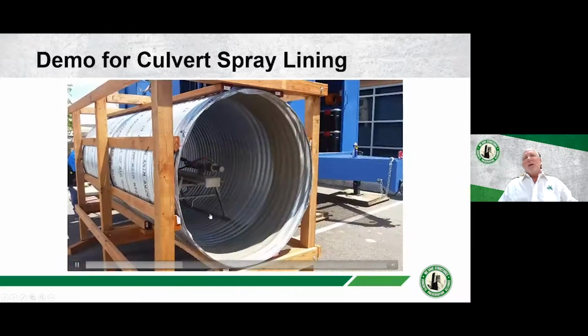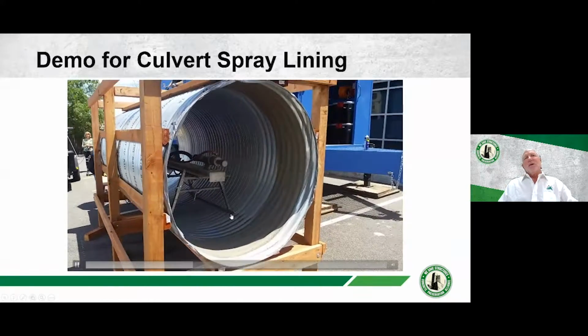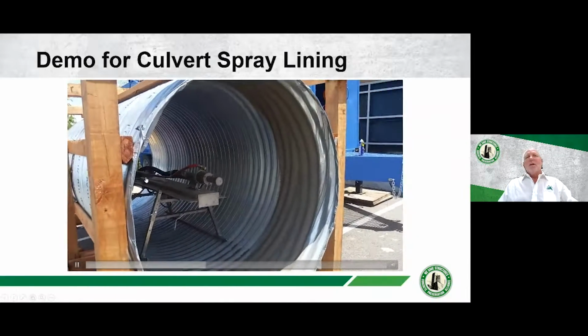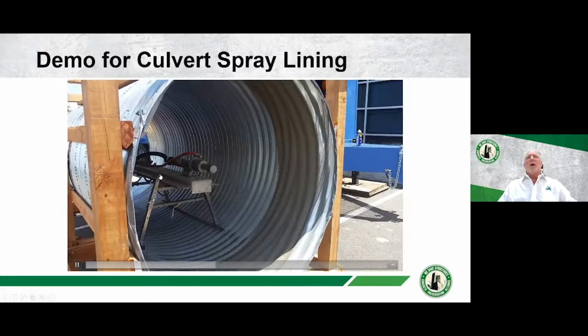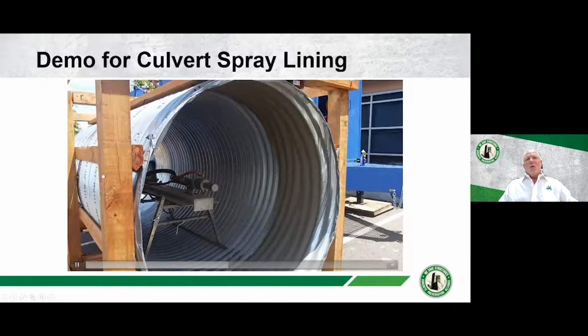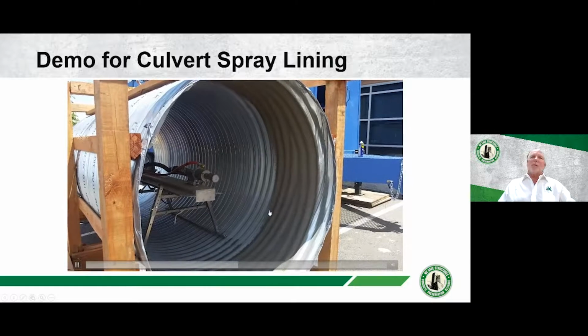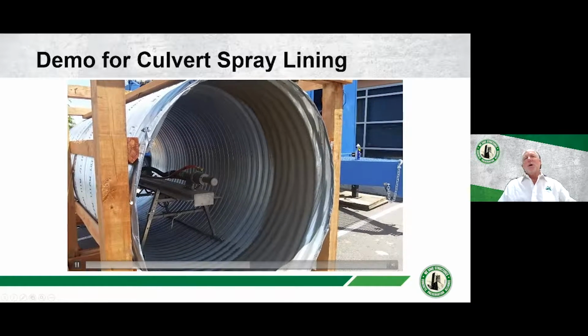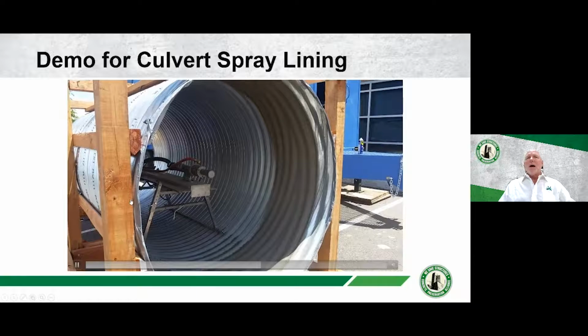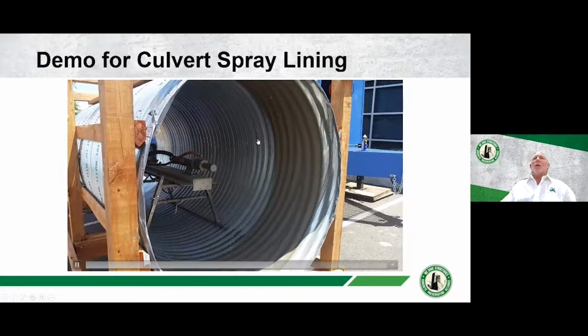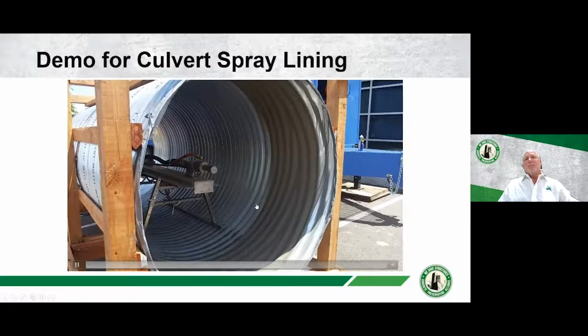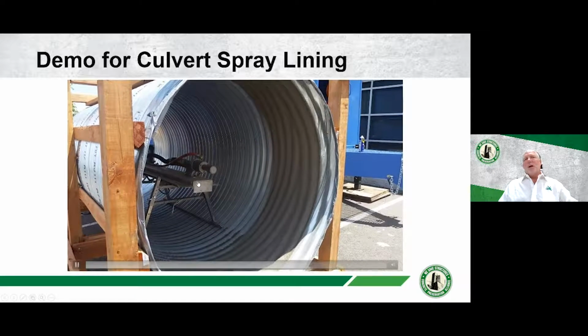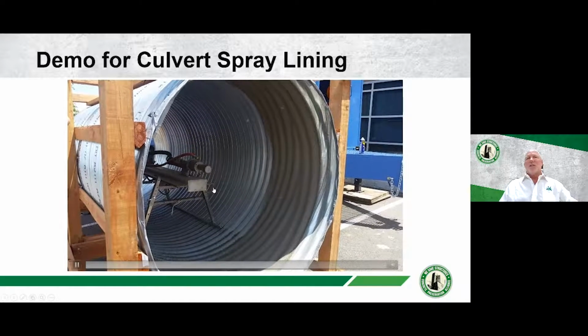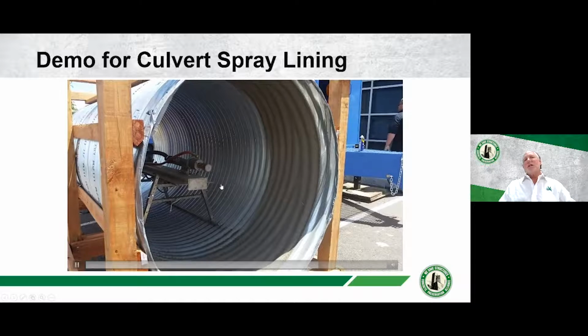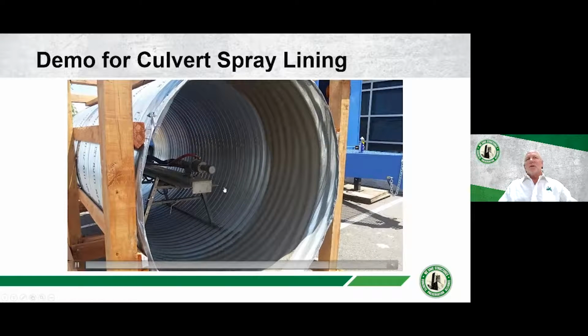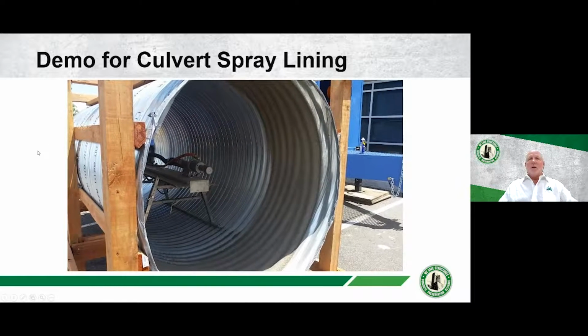The way it works is that this sled here is pulled back slowly at a specific rate. And we actually have calculations to say, okay, with this certain amount of material being pumped down the line, what speed do we have to pull this sled back so that we get a uniform thickness on the wall? And so that works out really well. Generally, with culverts, we're going to be spraying thicknesses of somewhere between half an inch and 1 inch per lift, and that all depends on how much material we want in the long run.